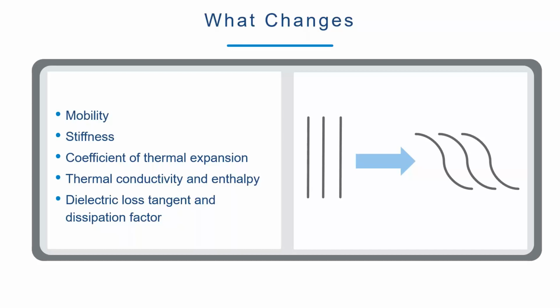The coefficient of thermal expansion is higher above the TG. Thermal conductivity is generally lower above the TG, but there are enthalpy changes that are evident right at TG. Dielectric loss tangent or dissipation factor generally increases above the TG. So we can measure each of these phenomena using the techniques I'll discuss in the presentation. And the results from the different measurements are not always exactly the same, but they generally occur over the same range.